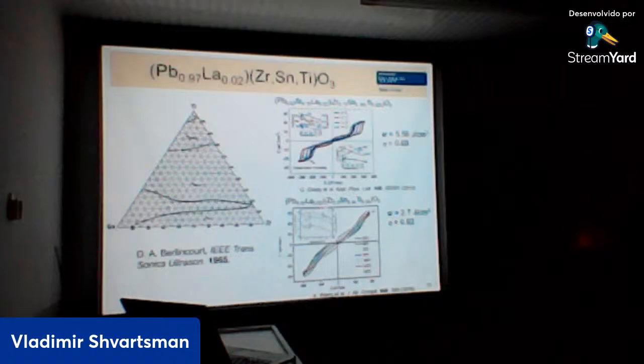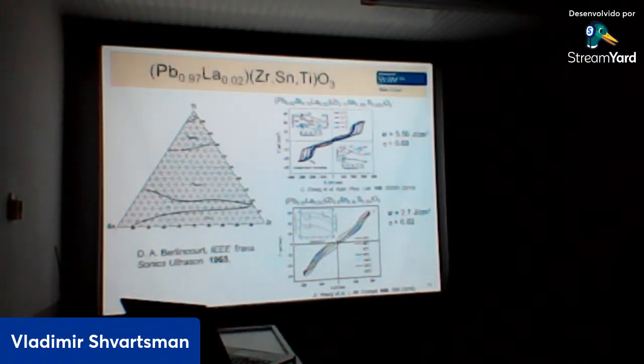So we can introduce, for example, more. We take out strontium, change concentration of tin, introduce more tin, and we can reduce this hysteresis. Therefore, you see the efficiency is going up, but in parallel the stored energy goes down. And when you look now in literature about the energy storage, these parameters are always kind of counterplay. When the stored energy goes up, the efficiency goes down. When you would like to have a large efficiency, your stored energy will be less. So you always again have to find a compromise.